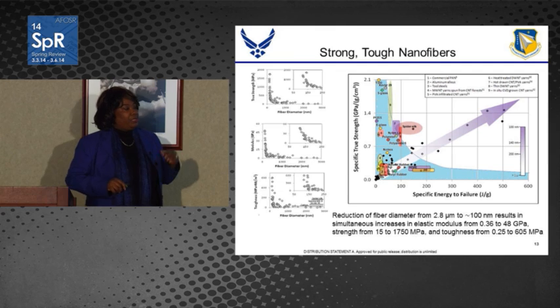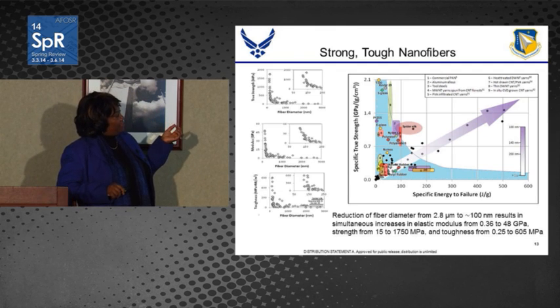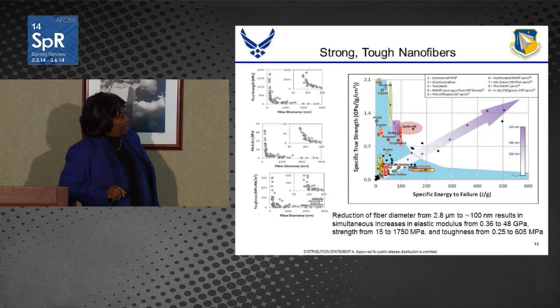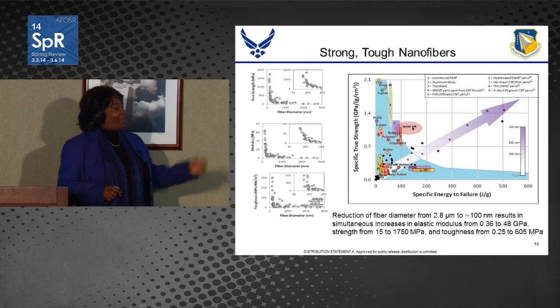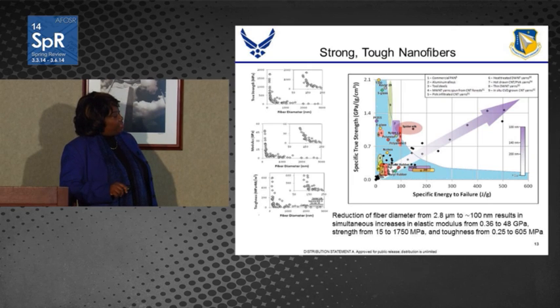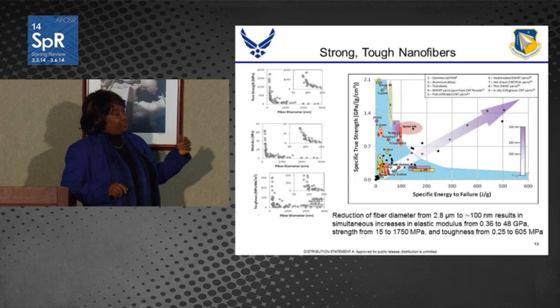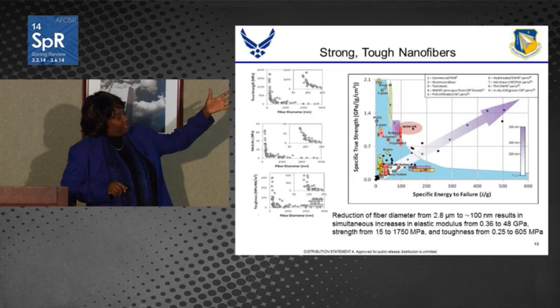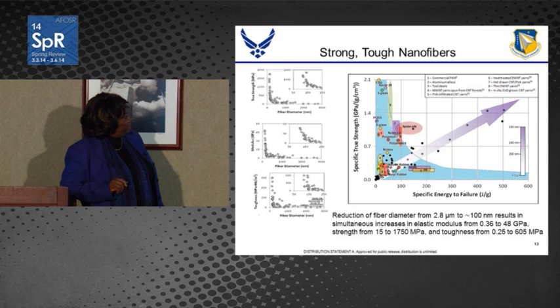But this arrow here shows the data for these electrospun polyacrylonitrile fibers, where for increasingly small diameter fibers, you see both an increase in the strength of the fibers and an increase in the toughness of the fibers. And so this was kind of an unexpected thing. As I mentioned earlier, the real goal here was to make polyimide fibers, but they started out with polyacrylonitrile fibers and have found these interesting things. And now we're looking more at understanding what's going on in terms of the orientation and the crystallinity that develops in these materials as you electrospin that can yield these types of properties. And so you see here in the data toughness, modulus, and strength, you see an exponential increase in those properties as fiber diameter decreases.